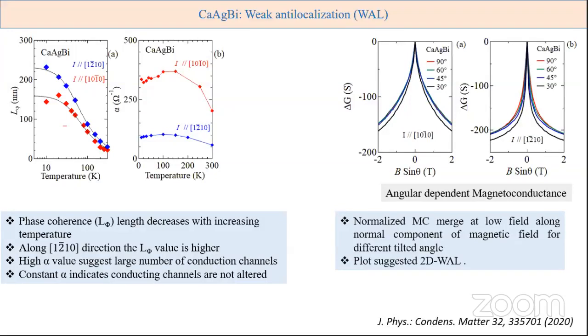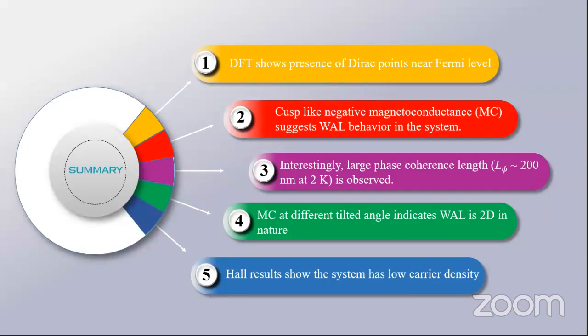In summary, I want to conclude that DFT shows the presence of Dirac points near the Fermi level, and it has cusp-like negative magnetoconductance, which suggests weak anti-localization properties. Interestingly, it has quite large phase coherence lengths, and the magnetoconductance data indicates that the weak anti-localization is 2D in nature, even in this bulk system, and the Hall resistivity shows it has quite low carrier density.